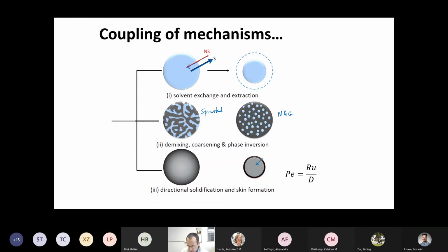And I think a good way to think about this is with this dimensionless number, the Peclet number, that effectively tells us what is the ratio between the speed at which the droplet shrinks, so the velocity of the drying front, compared to the kinetics of the diffusion of the solute. I like to think of this in terms of maybe a surfer at the beach and a big wave coming, and the options are, if the surfer is able to swim or to surf ahead of the wave, then the wave will continue to recede and you create a compact particle. But if on the other hand the wave is way too fast, then the surfer will stay at the extremities, and you'll create a skin instead. All the surface will stay out there. No one was able to catch the wave because they couldn't diffuse fast enough.